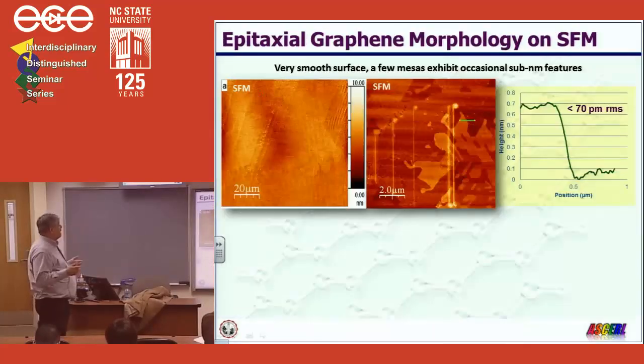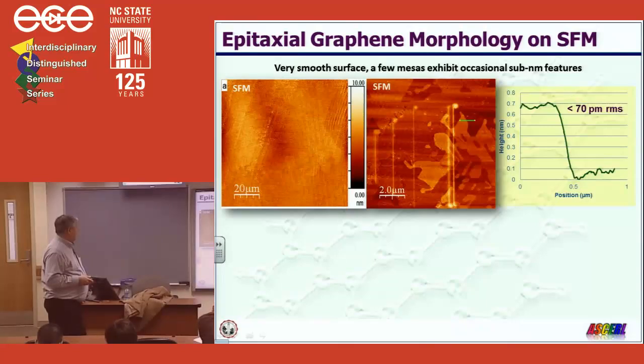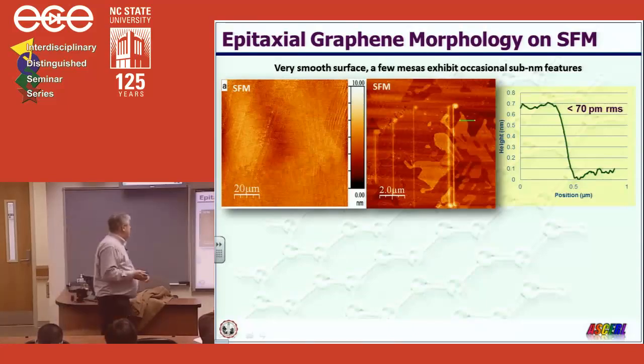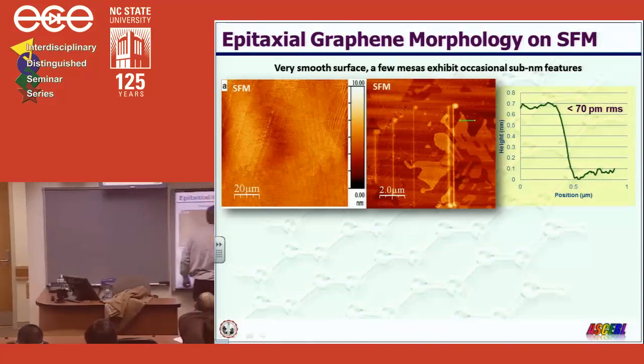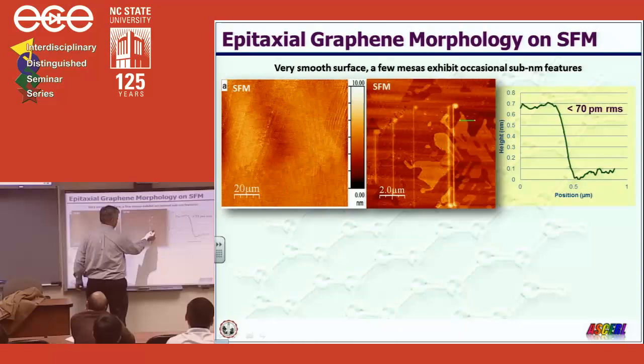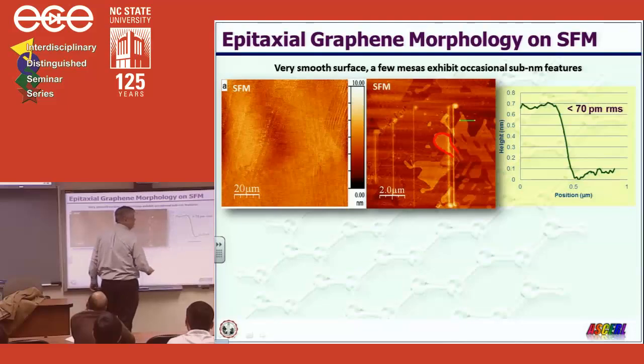And so I'm going to look for those, and those are the ones I'm going to do my work on. And here's an example of one of these flat mesas, looking at an AFM picture on the left, and it's basically instrument limited. We found a couple mesas that had little tiny bumps on them. That's shown here on the right. You can see the change in contrast here. And so this area is slightly higher than that area, and for this particular example, the height difference is about 0.6 nanometers.